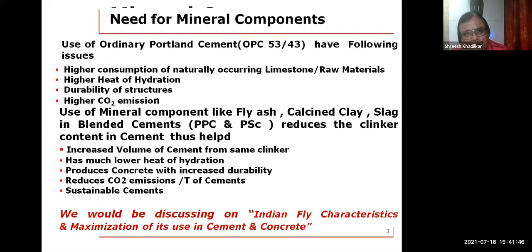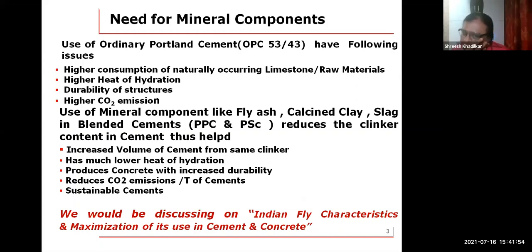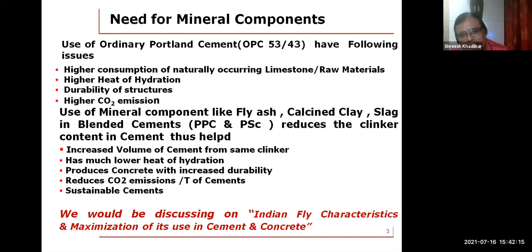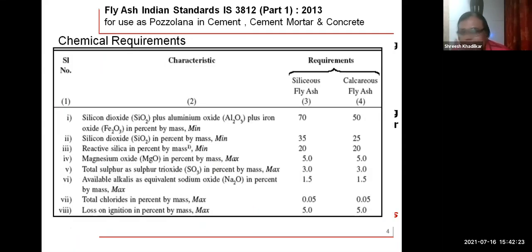Not only do these mineral components increase the volume of cement from the same clinker, but in concrete they also improve heat of hydration and all durability characteristics, giving structures a longer life with less maintenance required. According to the BIS 2013 specifications, we have siliceous and calcareous fly ashes. Calcareous is not very abundant except from lignite-fired power plants — most Indian fly ash is low-lime Class F by ASTM classification, with lime content of hardly one or two percent.